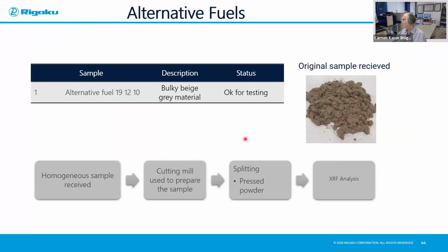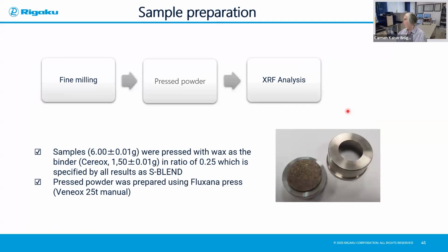Here's the next example, which looked like this after cryogenically milling the sample. And after cryogenically milling the sample, we prepared the sample with a wax to make it a nice stable pellet that we can press. And you can see this is what it looks like.